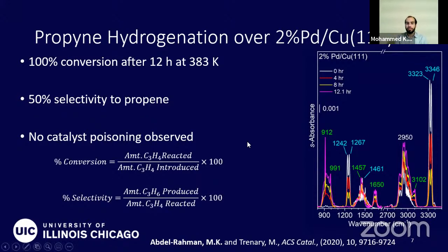And another observation that we made is that after 12 hours, we noticed that the catalyst hasn't been poisoned. If it was poisoned, we would have still seen some propyne remaining in the gas phase, in the infrared spectrum. So the reaction went to completion with 50% selectivity to propene.